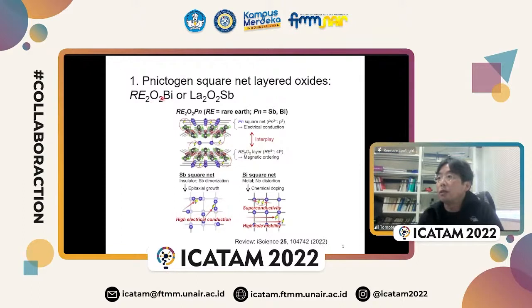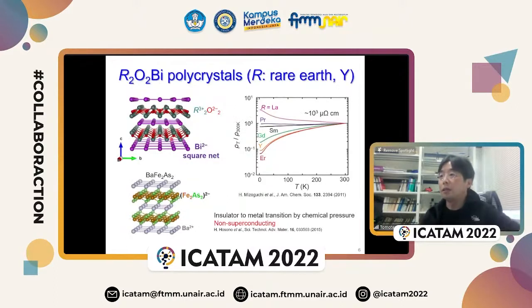The first one is the pnictogen square net layered oxides. This is the chemical formula, bismuth oxide or antimony oxide. This is the crystal structure, with a bismuth or antimony square net. This is a top view, and this is a rare earth oxide layer. This is the same crystal structure. In this case, the bismuth square net is electrically conducting, and the valence is negative. This is an unusual oxidation state. And this rare earth oxide layer is an insulating layer. This structure is similar to the iron-based superconductors, high-temperature superconductors.